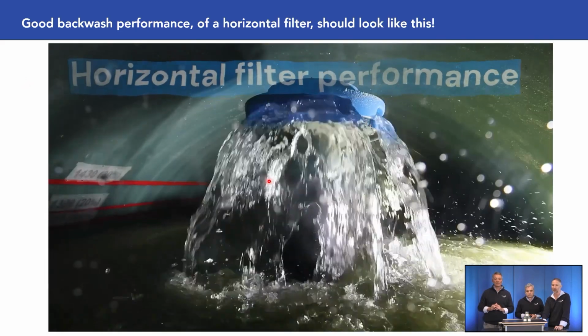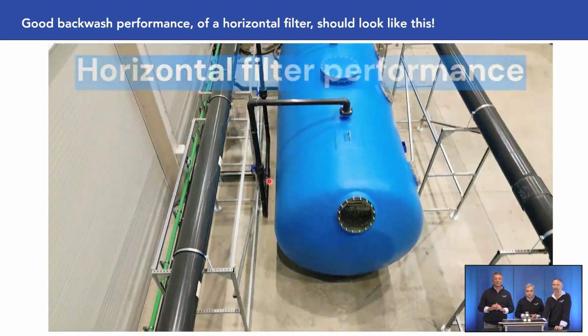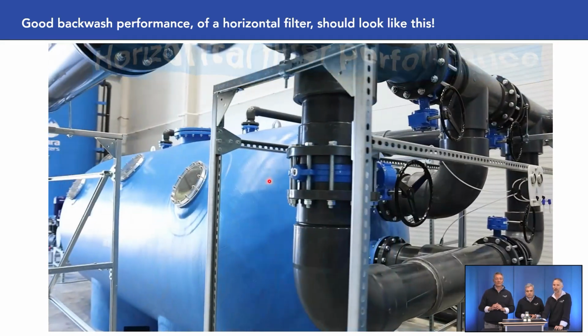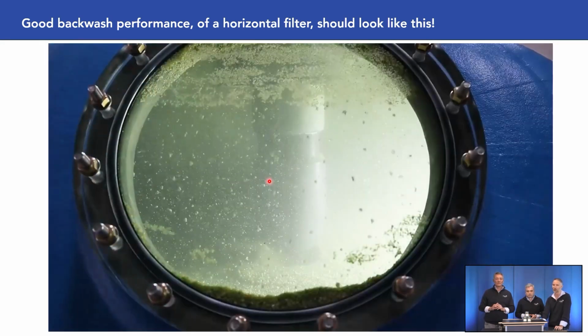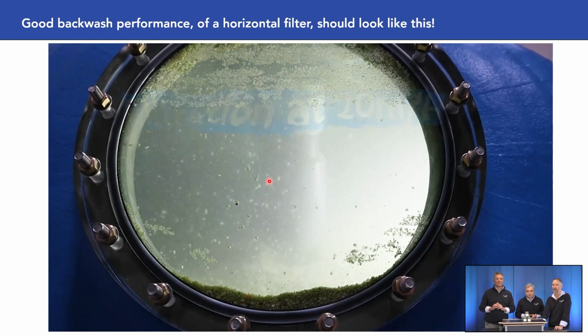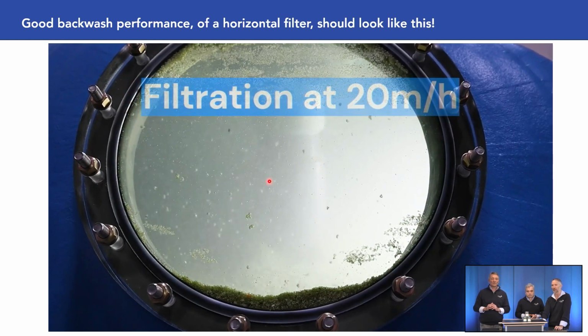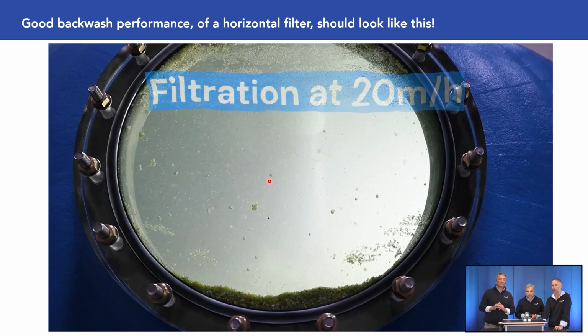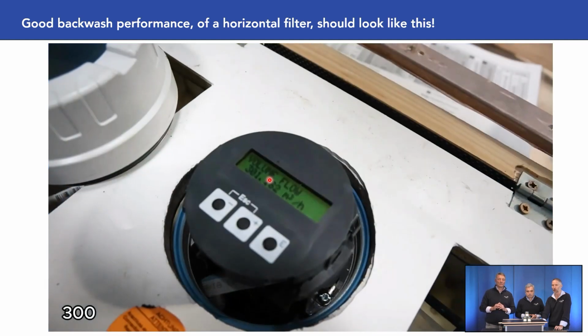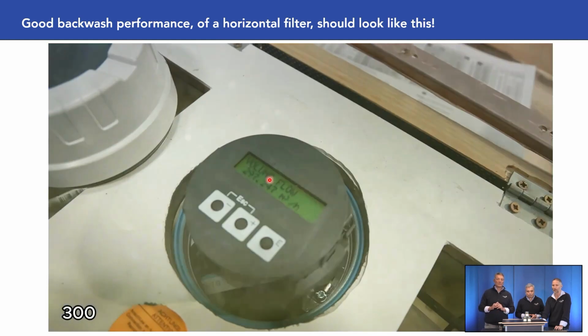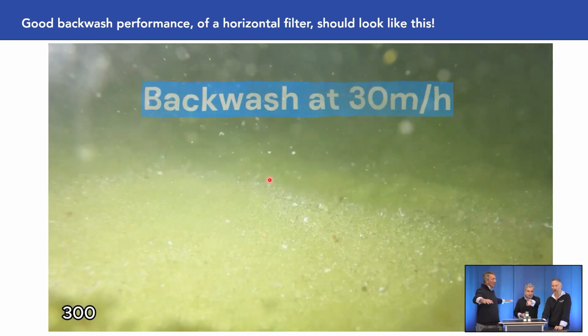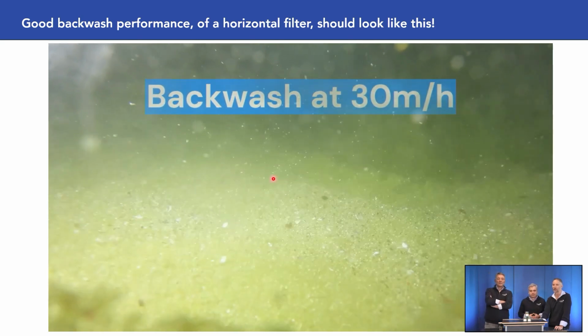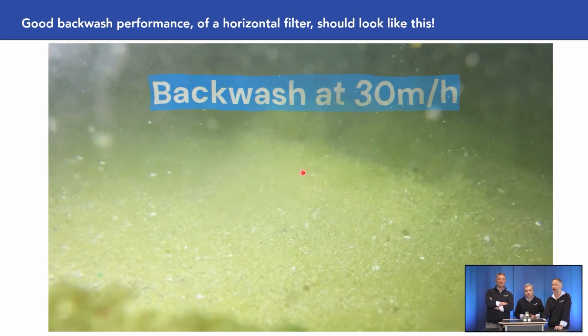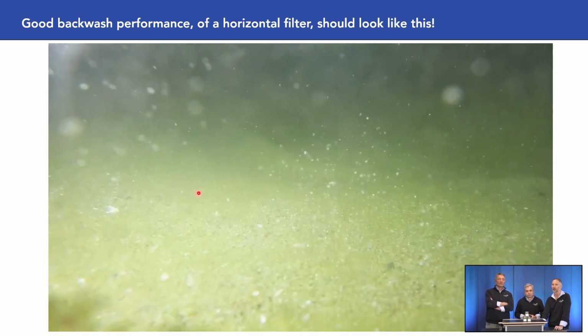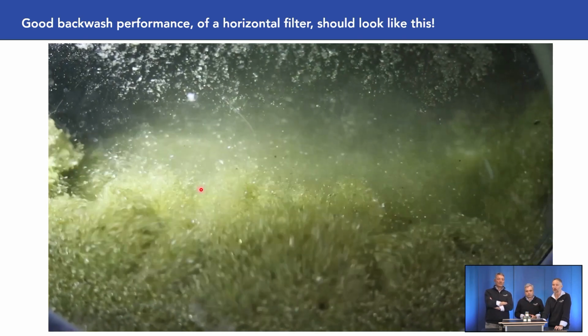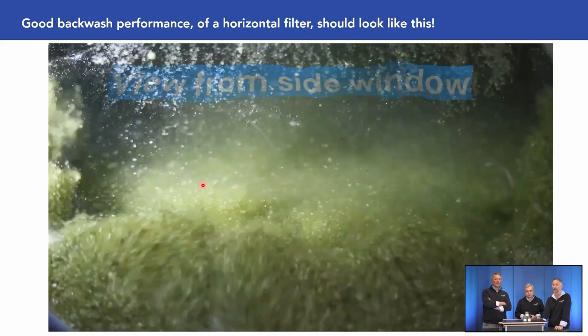Filtration performance, there you can see we were monitoring the different bed depths and the expansion capacities during the process. This was at filtration at 20 meters per hour, just to make sure that the bed was not moving in any way and wasn't kicking up on the sides. So the flat bed was absolutely flat. Then the first backwash was at 30 meters per hour, and you can see really great fluidization. We achieved the 20% bed expansion.